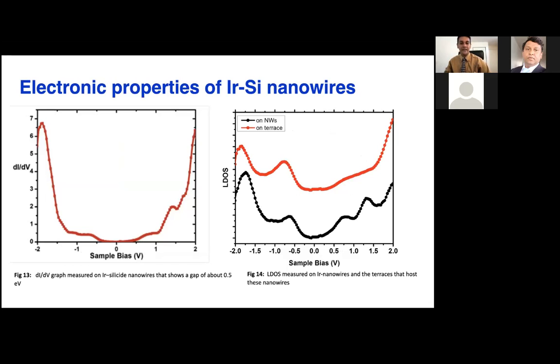Then after that, we did the LDOS analysis on the nanowires as well as the terraces that host these nanowires. Here, in Figure 14, the black line shows the LDOS curve for the nanowires, and the red line the LDOS curve on the terraces. There's also a difference curve between the nanowire and the terraces. Above the Fermi level, the nanowire has well-resolved surface states. That is mainly because of the reaction between the iridium atoms and the silicon atoms, and some part came from the step edges of the surface.